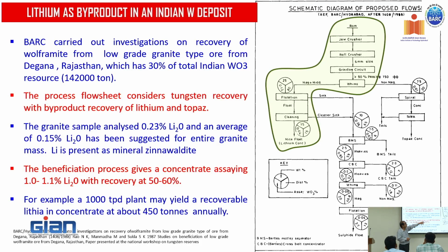tungsten, there is a mineral called zinnwaldite. It is mostly present in mica. So I have just circled this. It goes through crushing, grinding, and wet high intensity magnetic separation. Always remember that these micaceous minerals are weakly paramagnetic. So during the wet high intensity magnetic separation followed by flotation, they get enriched in the mica fraction.